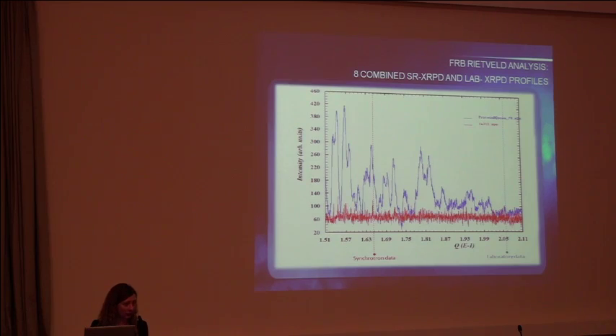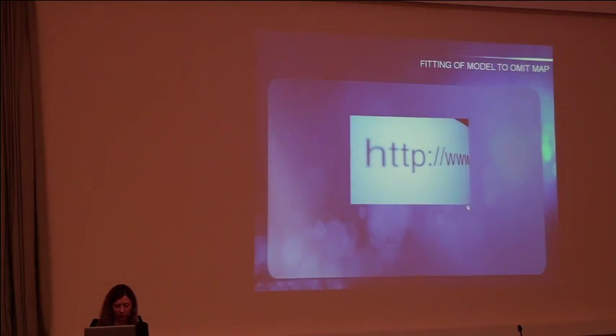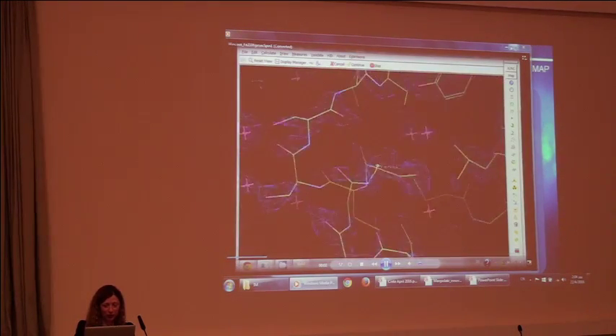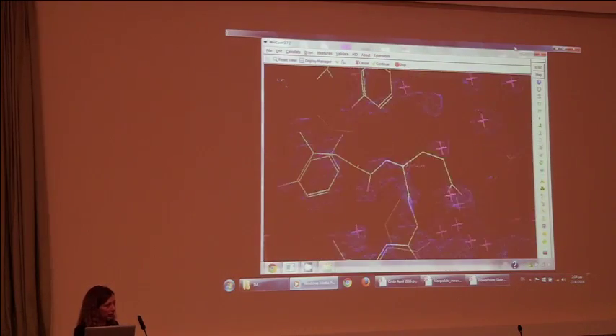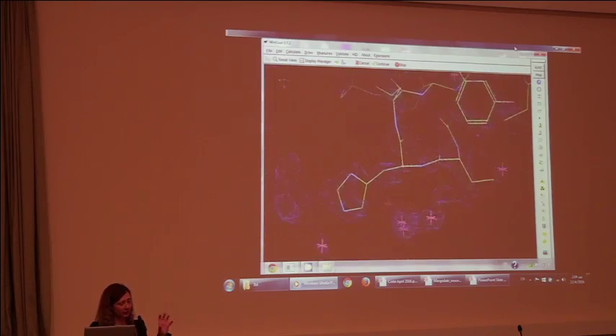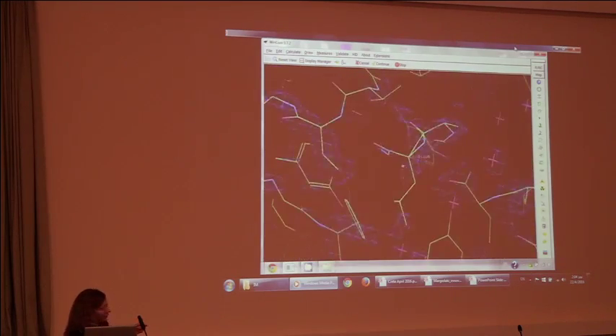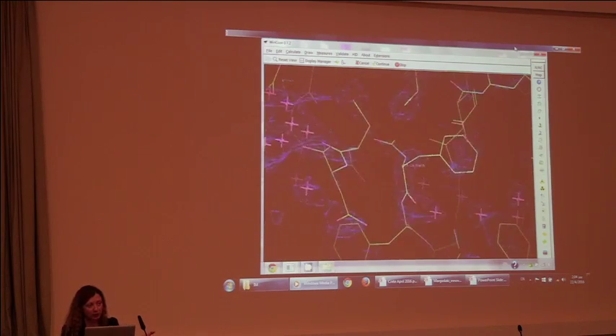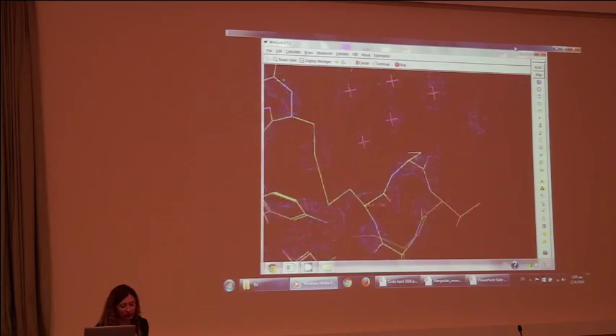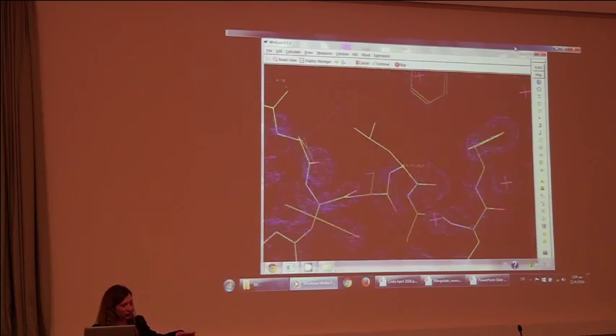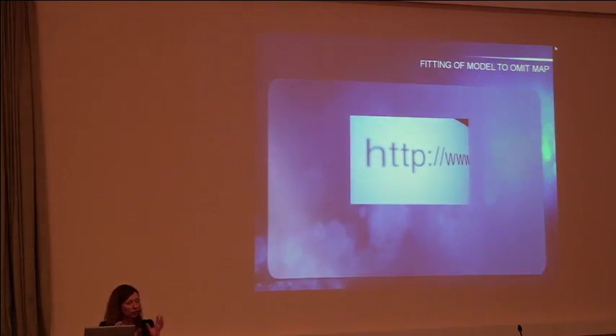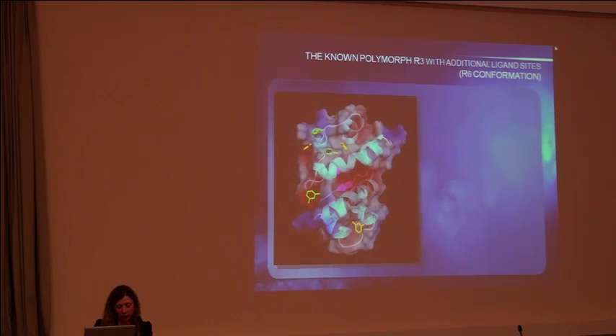We reached approximately 2.5 angstroms, and the total omit maps that you will see here were sufficient for completely refining the structural model and identifying where m-cresol sits on the protein surface. This is Coot. It's a software designed for single crystal data, but programs do not understand if you have other than single crystal data. It fits the protein structure in your electron density map. And as you saw the electron density, this combination of diffraction profiles was sufficient for completing the model. And not only the protein, but also the ligand sites were identified.